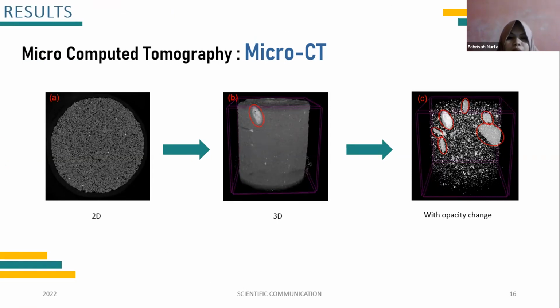In figure B is a 3-dimensional view of the sample image. It can be seen that the small grains dominate the entire area of the sample. So there's a possibility that the sample belongs to the type of sandstone. It's a sedimentary rock. However, if you look at the red circle in figure B, there are areas with brighter contrast than the other areas. So this can be explored further by adjusting the opacity.